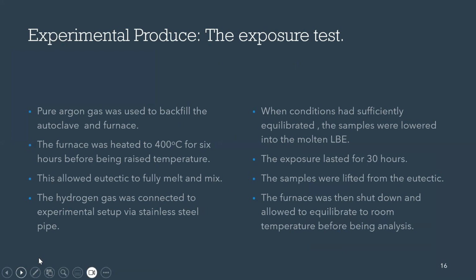So, experimental procedures, the exposure test. This part talks about pure argon being used to purge the autoclave and furnace. And the furnace was heated to 400 degrees Celsius for 6 hours before the temperature was raised to 700 degrees Celsius. This process allowed the LBE to fully melt and mix.